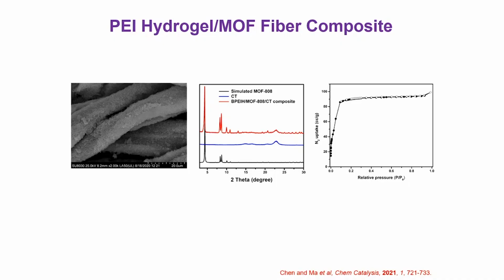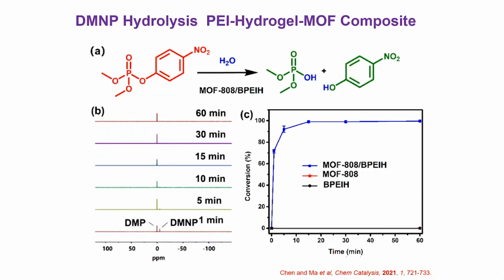Once again, we maintain crystallinity and porosity. More importantly, when we do the catalytic reaction with the simulant, and you could imagine the agent is even faster than this, now we are everything in the solid state, and we have a half-life of less than a minute. So at this point, as a professor at Northwestern University, you say, what else can I do? Because I very much got to the point I could get it to this point. And I will tell you later on where we took it from here.